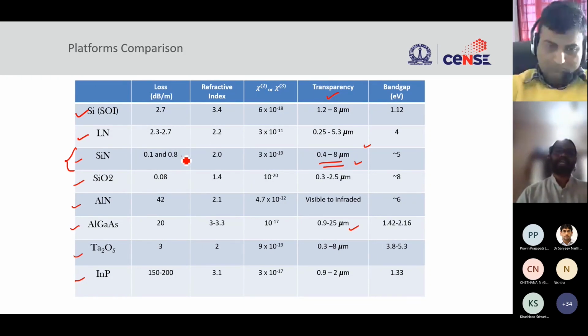And then the other interesting thing is the loss. What is the propagation loss? And this is not meter, this should be centimeters. So you can get reasonably low propagation loss, because you're talking about light propagating through a waveguide. You don't want light to be lost when it is propagating through a waveguide. This is like resistance to light flow, so you want that to be minimum. Silicon nitride seems to be at the right spot, looking at the various parameters that we are looking at.